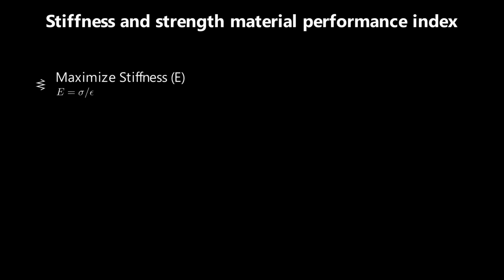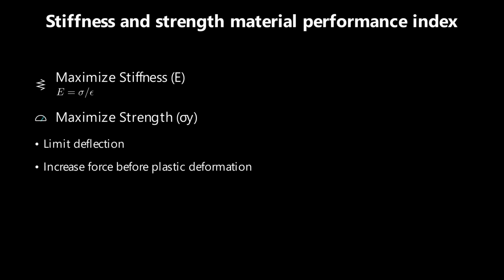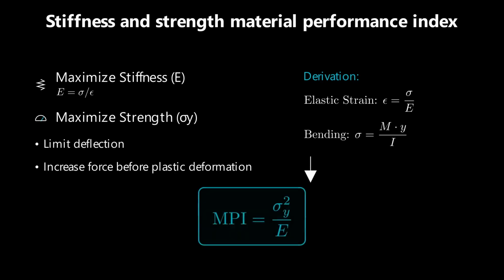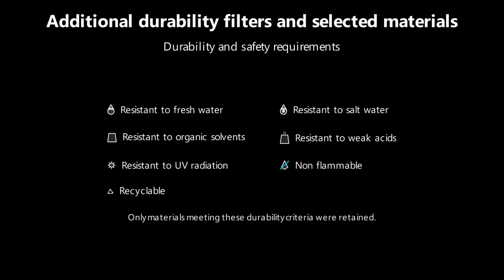We want to maximize the ratio between stress and strain, or Young's modulus, and also maximize the yield strength of the material. This will limit deflection and increase the amount of force that can be applied before plastic deformation. By rearranging the equations for elastic strain and bending, we get that the MPI equals yield strength squared over Young's modulus. There are also durability requirements necessary for an outdoor metal object. We applied additional requirements around the material's resistance to freshwater, saltwater, organic solvents, weak acid, and UV radiation. It should also be unflammable and recyclable.